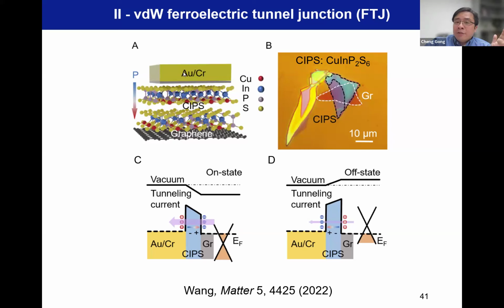As I showed before, you use two different metals. Here, one is a 3D metal, chromium. The other one is a 2D metal, graphene. And then separated by just a few layers of CIPS, copper indium phosphorus sulfide. And when you flip the polarization, the inherent dipole within the CIPS will change the tunneling barrier from one electrode to the other. So this will change the resistance dramatically.